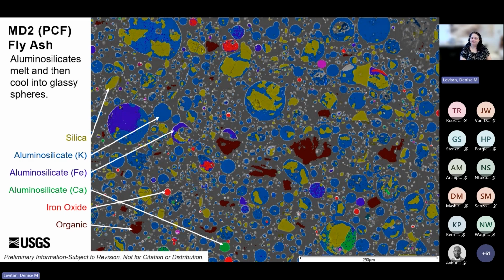And this shows the different fate of calcium when it's not reacting with the sulfur within this higher temperature environment. Then we also see some of these smaller iron oxide particles and larger pieces of residual organic carbon. And just to note, these two images, this one and the previous one, are both on the same scale, where this scale bar is 250 microns, or a quarter millimeter.